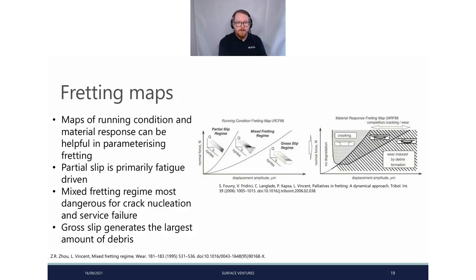In addition to our fretting logs, we have fretting maps, two of which. The running condition fretting map: at lower displacement amplitude, with whatever normal force it is, we have partial slip. Increasing the displacement amplitude, we have our mixed fretting regime. And then at the highest displacement amplitude, gross slip. One thing to mention is that should the displacement amplitude go so high as to entirely reveal part of the wear scar during any part of our process, that transitions into full sliding. We're no longer in fretting because we've essentially lost some of the fatigue component.